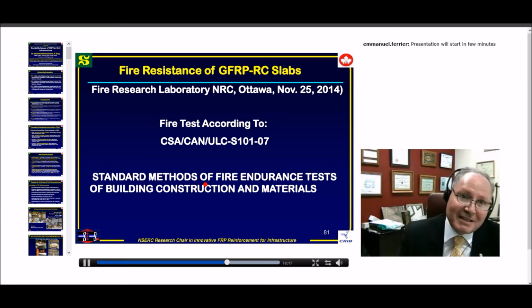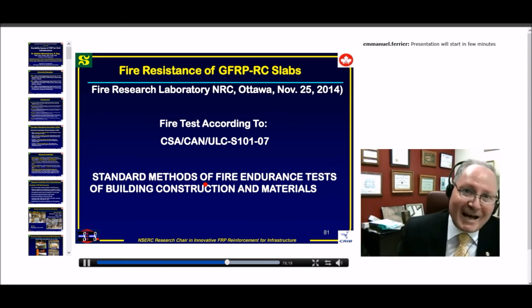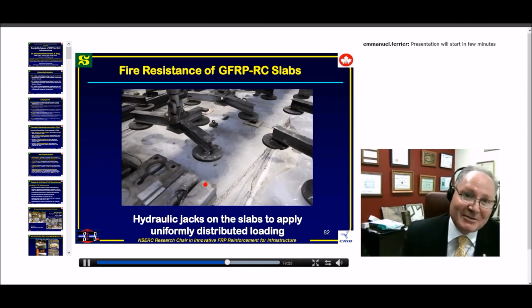because, can you imagine, depending on how much time the slab will last, it could have a big effect on the whole industry. This is showing the hydraulic jack, from the top of the slab. We applied uniformly distributed loading, exactly as it has to be done, and we generated in the tensile reinforcement at the bottom about 2,800 microstrain, which is a little bit above the service strain expected in the field. So it was really done properly.